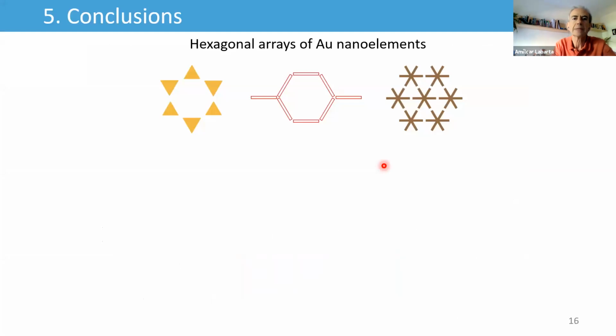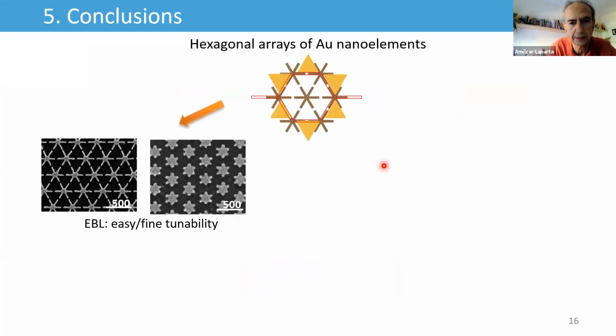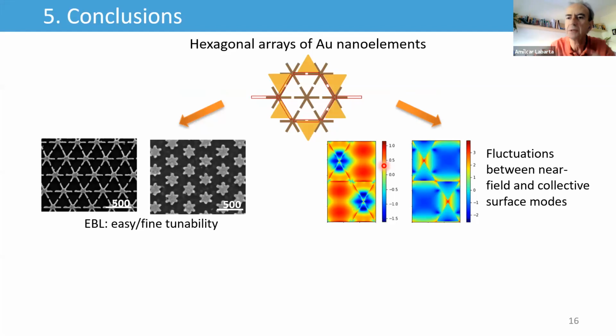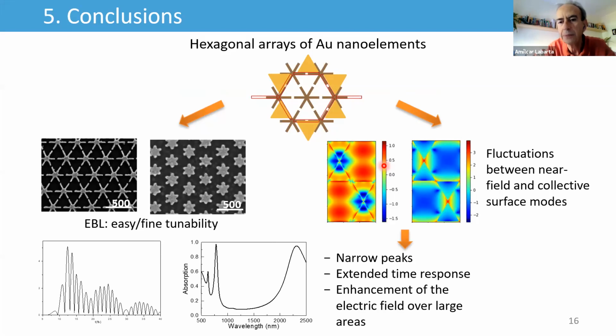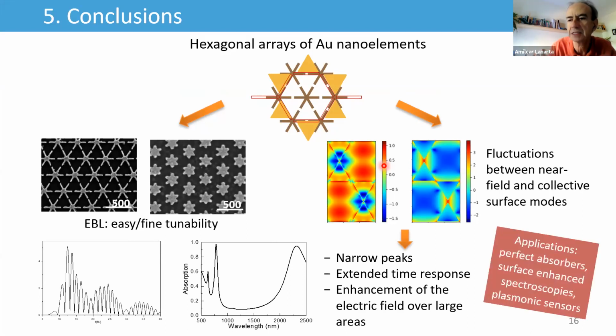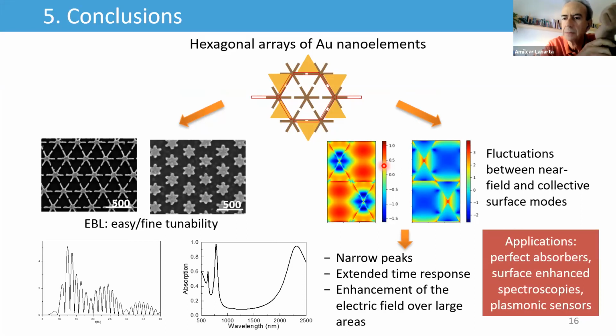So these hexagonal arrays of gold nanoelements can be fabricated, as I have said, by electron beam lithography. This technique shows fine tunability. This kind of system fluctuates between near-field and collective surface modes, and these collective modes are associated with narrow peaks. They give extended time response, and we observe enhancement of the electric field over large areas. So these kinds of systems could be suitable for applications as perfect absorbers, surface enhanced spectroscopies, as Javier will show you in the next talk, and plasmonic sensors.